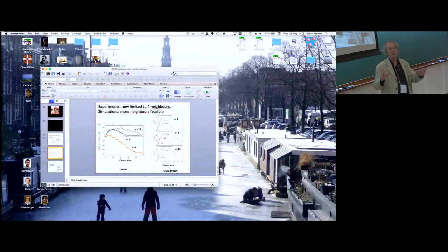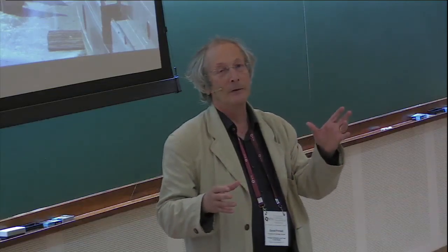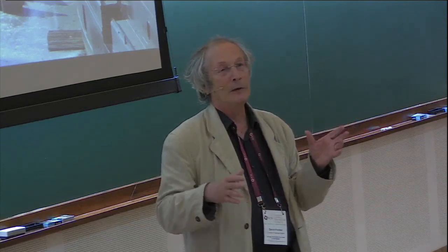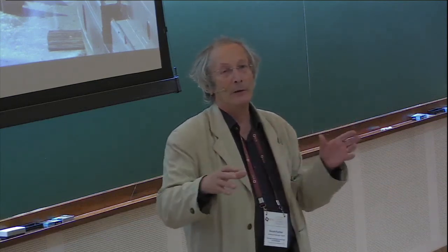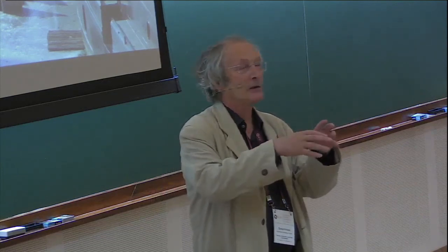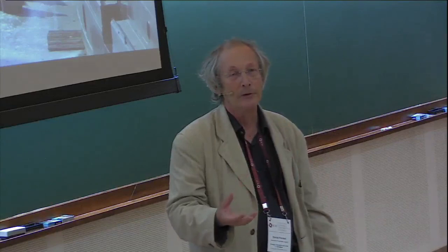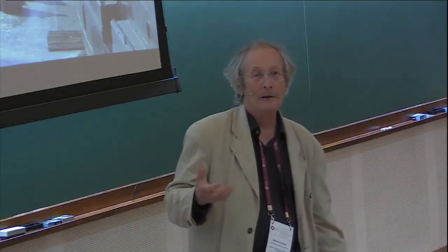And the reason why it's not a good idea is that if all the binding strengths are the same, then any part of the structure could act as the critical nucleus. And so basically by the time it goes, everything goes. If you have a subset that binds more strongly, then that acts as a seed on which the rest can grow. So first of all, you want the binding strength to be not all the same. And I think that is one thing.